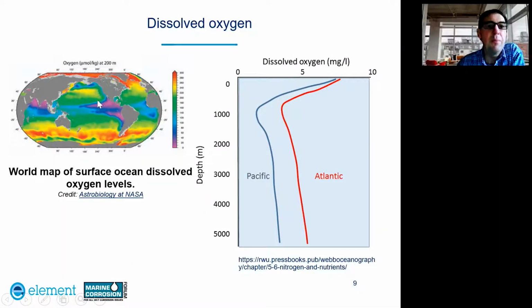Generally it follows the pattern for the surface sea temperatures, because the oxygen is dependent on the oxygen in the environment, which is fixed at about 20.8%, and then the solubility of oxygen in the seawater is dependent on the temperature of the seawater, with the lower temperature having the highest solubility of dissolved oxygen. So going through the depth of the sea, at the surface, although the temperature is higher, the dissolved oxygen is also higher. This is because you've got the air with 20.8% oxygen close to the surface of the sea, so that's obviously picking up a lot of oxygen from the air.